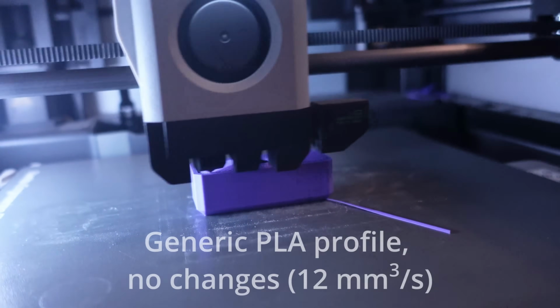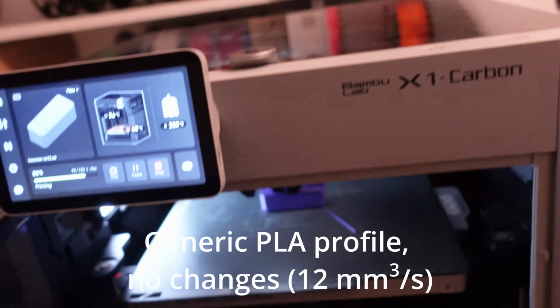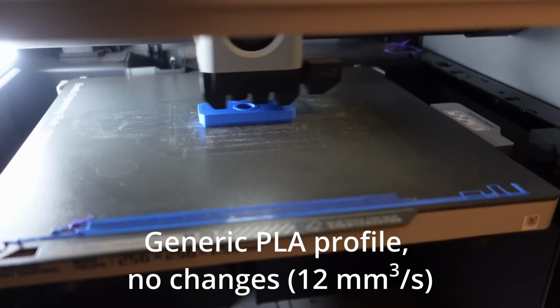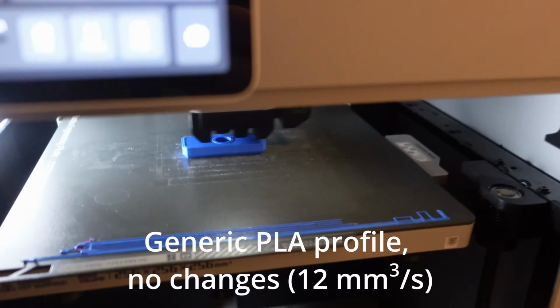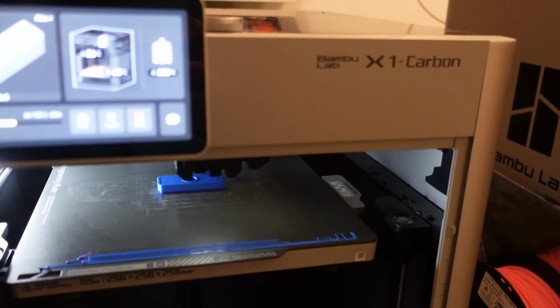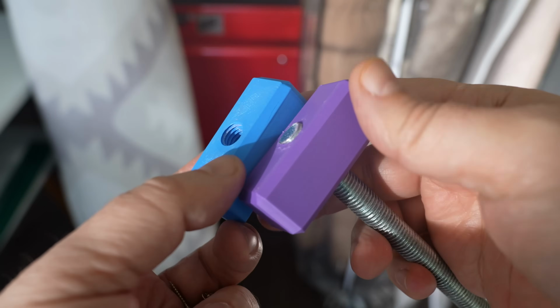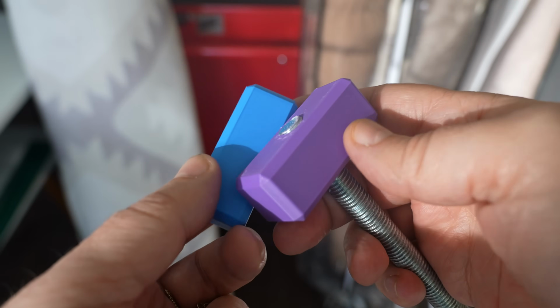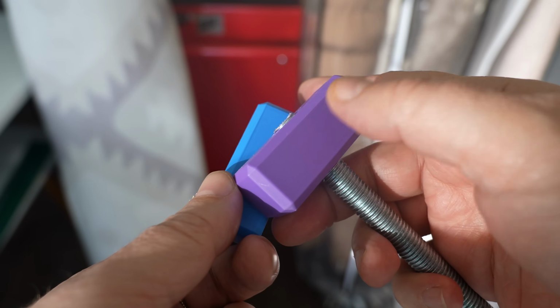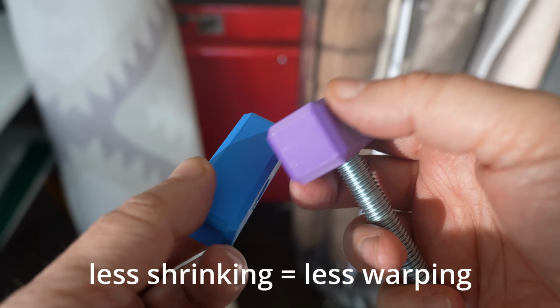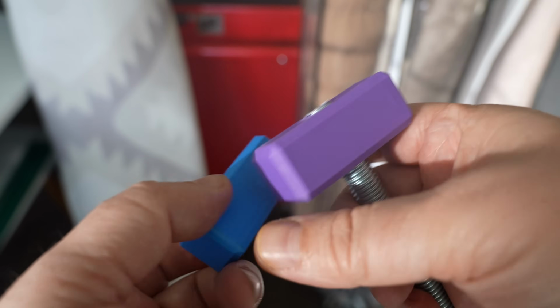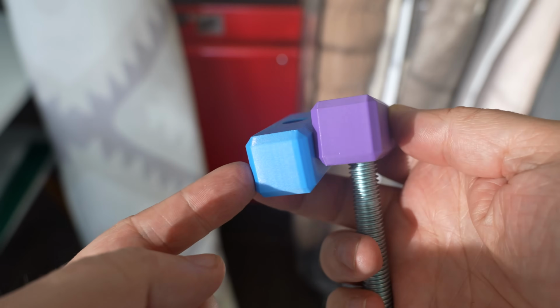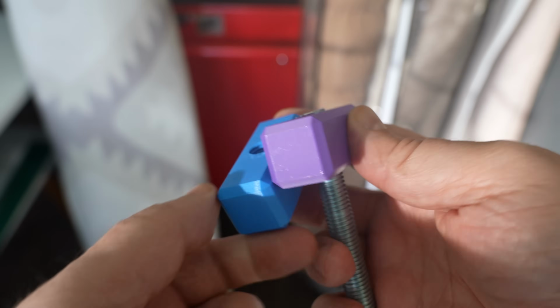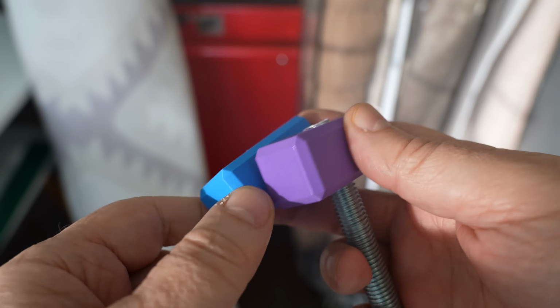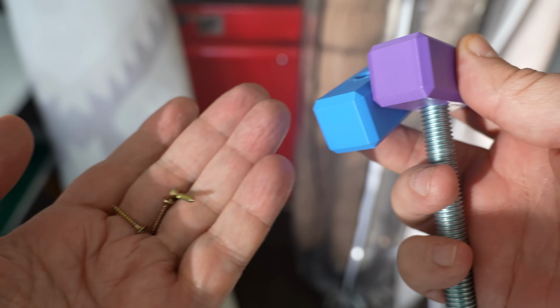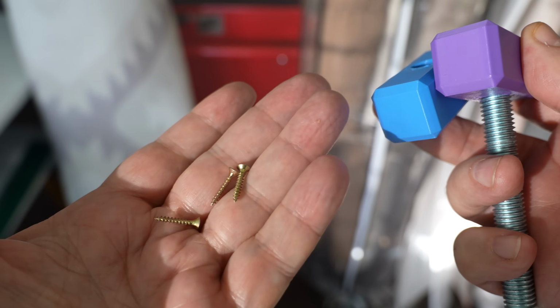Just for curiosity, I printed this hammerhead on X1 Carbon and I used the engineering plate with glue on it, and the same G-code, same file as the regular PLA. This time the printing was much easier with the Super PLA Plus because it has 50% infill and 5 walls. It is not completely solid inside, and I used the glue. And I printed these test objects from one of the cheapest PLA, and I used completely the same G-codes. I'm just curious how much damage we will see if I try to hammer something into the wood.